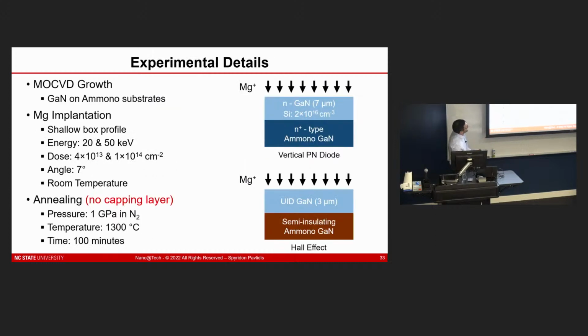And so for this first experiment, we implanted the magnesium, and after we implanted the magnesium, we annealed it at 1 gigapascal nitrogen overpressure at 1,300 degrees, and a relatively long time as well, about 100 minutes here.